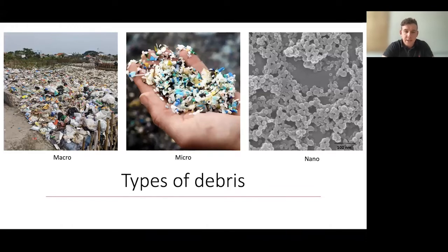It's important to flag early on that 'plastic pollution' gets used as an umbrella term, but it's not just one type. Plastic comes in many different size categories: from macro plastics, typically anything bigger than 20 millimetres, up to mega plastics, down to micro plastics — where much of my research has been — which were originally defined as less than one millimetre. These truly microscopic components form from the degradation of larger plastics. The definition was later changed by the EU and NOAA legislation to five millimetres, which is the general consensus, to incorporate a wider range that may cause harm. And finally, right down at the very small end we have nanoplastics, which remain a bit of a mystery — even some of the best analytical equipment can't detect them, so their impact is still unclear.